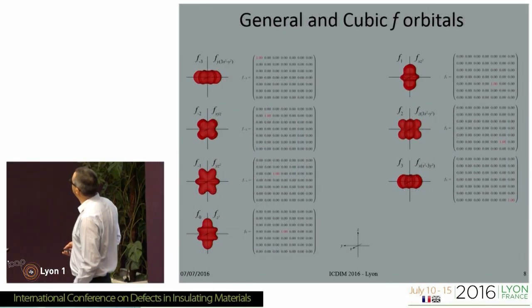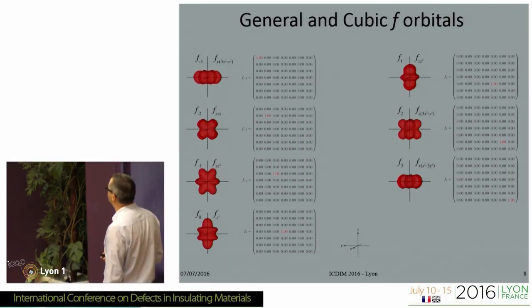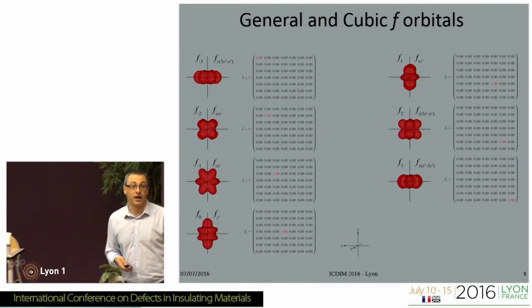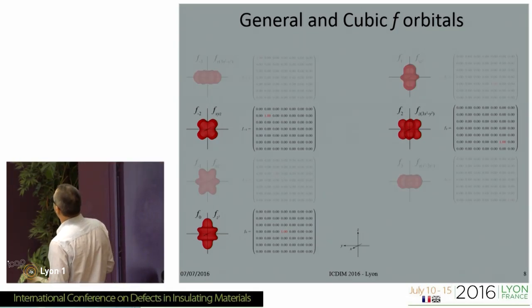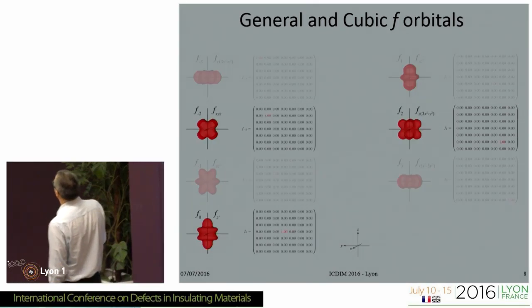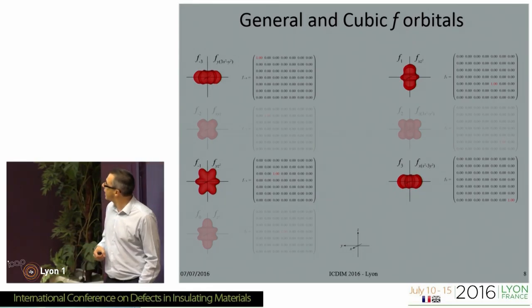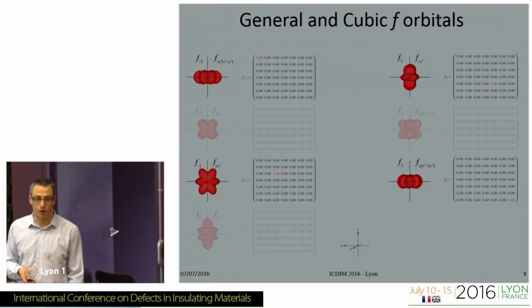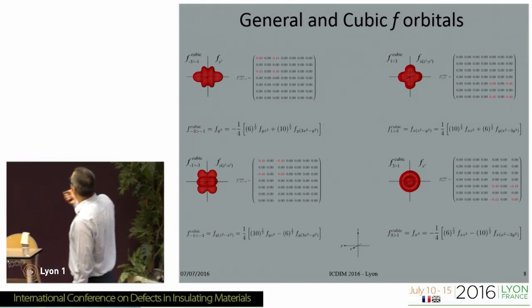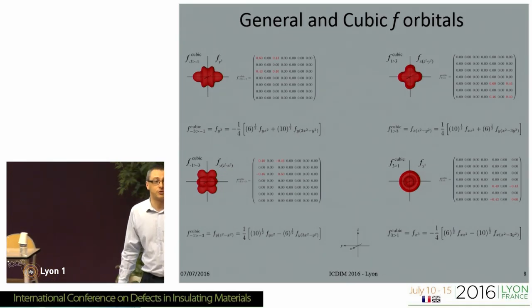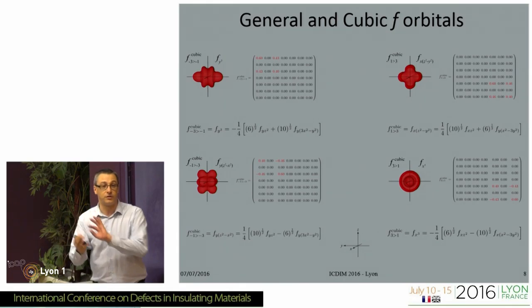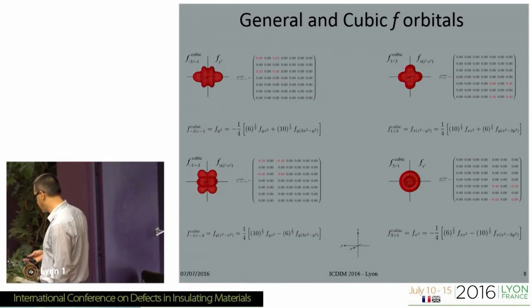For the general F-orbitals, these are simply down the leading diagonal. Unfortunately for cerium and uranium oxide, we're in a cubic system, so we're better using the cubic F-orbitals. We have to take linear combinations of these to get the cubic set of orbitals. These are now appropriate for the cubic symmetry within our system, and you can see we've already introduced leading diagonals before we've even rotated the reference frame for the crystal field.